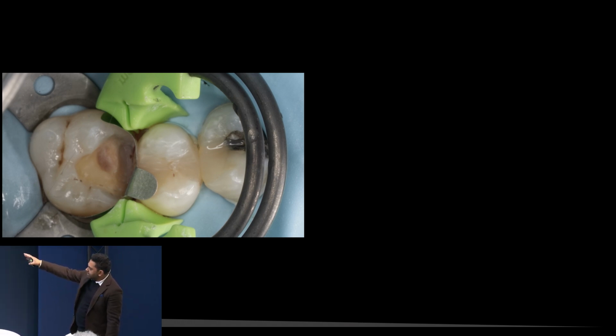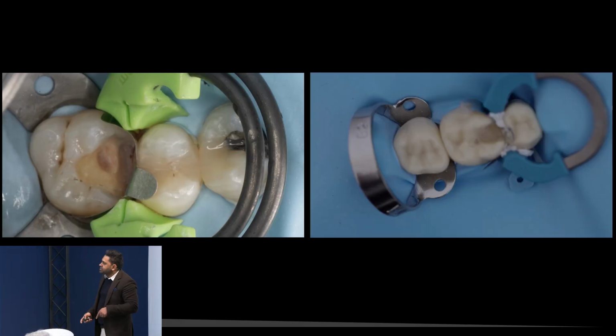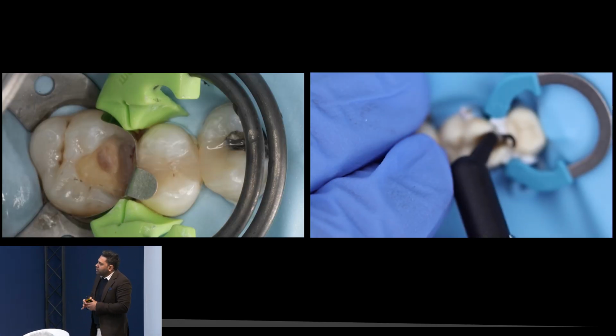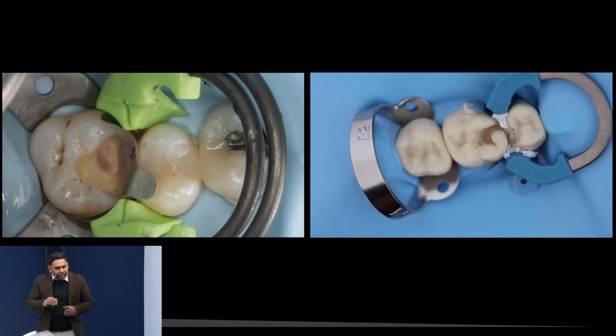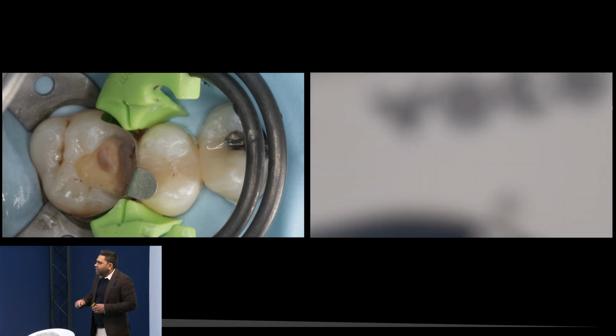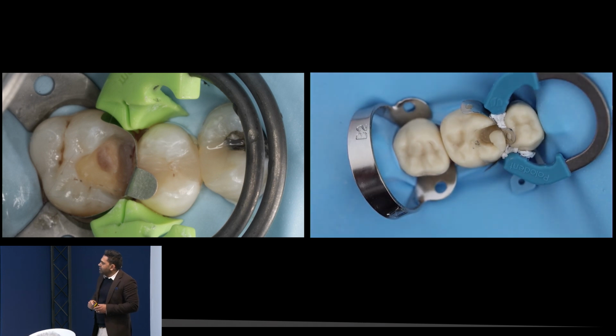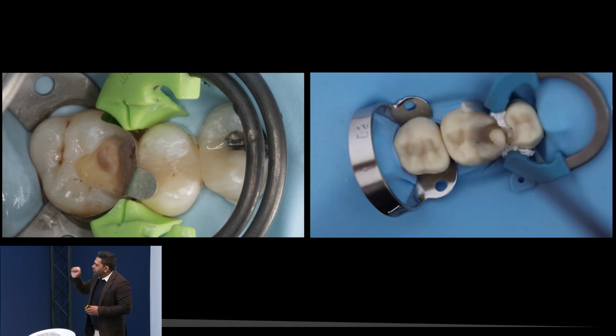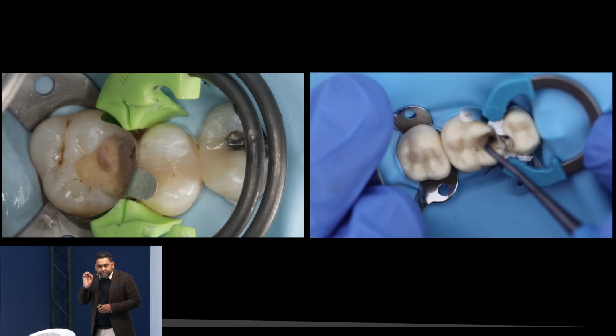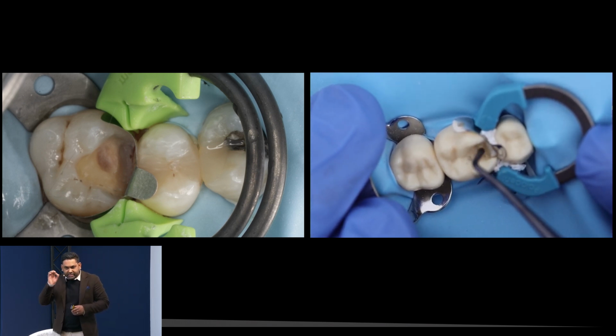The other big benefit is that it has a very wide metal matrix. Sometimes if it's too narrow and we've got a very wide box, the matrix doesn't quite encircle the whole circumference of the tooth. So this is a big advantage of this system. And when we've got a very rigid shape to the matrix, we can literally pack our material against that. The nice thing about the GrandioSO Unlimited is it's really easily sculptable. The big benefit is that it has a memory. You pack it and sculpt it and it stays where you want. So I think you're going to really like that feature.